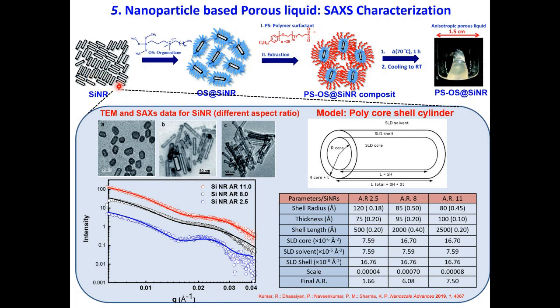Now this hollowness can be probed by small angle X-ray scattering. Of course, TEM can show you these pictures where you can see a shell and the hollow core, and these rods are of different aspect ratios, but these are only tens of particles which you can see from TEM. If you want to get an average value, you can use small angle X-ray scattering to probe these silica nanorods of different aspect ratio, 2.5, 8, and 11, and get all these parameters out. You can pull out shell radius, thickness, shell length, and a final aspect ratio as well.